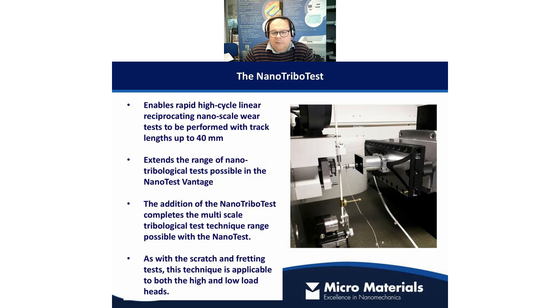It's worth saying we can do these tests with the high load and the low load head. Here we've got a test set up with our low load head, and this is our nanotribometer test stage. This stage will allow us to oscillate the sample back and forth, laterally with respect to the indenter. We can actually do tests up to 40 millimeters in track length, although in practice we rarely would do that.